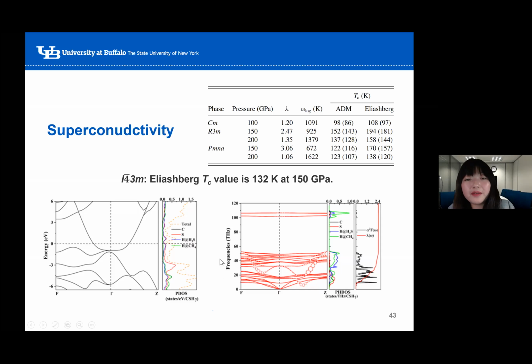So for the superconductivity, R3m at 150 GPa has a lambda that's almost twice as big as the Cm phase. Also, the lambda for the R3m phase is comparable to that found in the trihydrogen sulfide with high Tc. However, because the omega log is a bit smaller in the R3m phase, so is its Tc. For the R3m and Pnma phases, lambda decreases as pressure increases. And this is not offset by the increase of omega log, and therefore their Tc decreases as pressure increases.